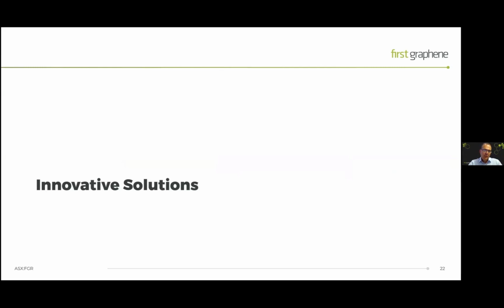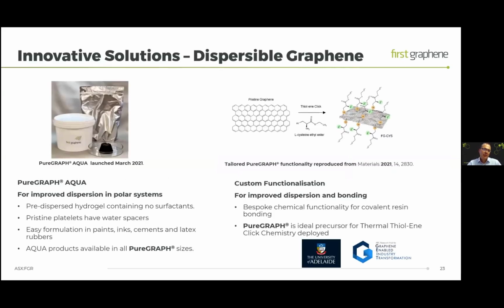We continue to look at innovative solutions, and we do listen really closely to our customers when they bring forward new problems and ideas. So we continue to develop the PureGraph range of products. And as I said earlier, the PureGraph Aqua is a product we launched earlier this year. It's a really interesting material because it's a commercially available graphene hydrogel. It contains no surfactants, so it's essentially just graphene and water. And the water molecules seem to be present as spacers between the pristine graphene platelets. And of course, what this means is when you're dispersing this into a polar or a water-based system, the separation of the platelets is more straightforward, and you get better dispersion of the individual platelets.